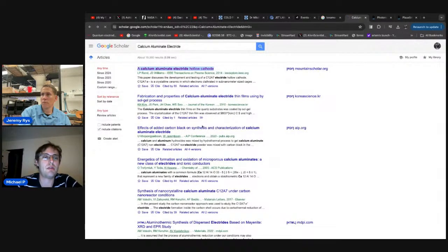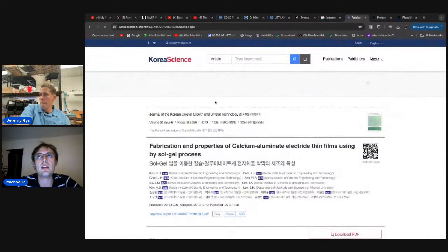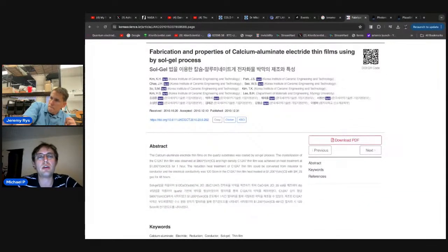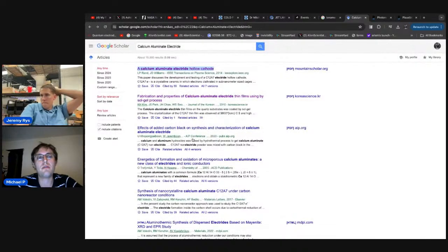That's extremely low. So you can get electrons to boil off of this stuff just by heating it to 300 Celsius, and then already enough of the Boltzmann tail is above 0.5 electron volts, where you get electrons evaporating off of the surface, basically. So that's cool.